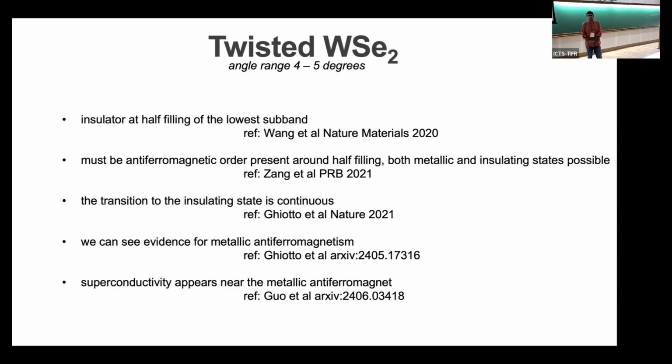One final question from Oscar, and then we should move. How sensitive is your insulator at nu equal to -1 to the external magnetic field, particularly if it's perpendicular? Yeah, that's an interesting question. It's fairly sensitive. By about 3 or 4 Tesla, you generally lose this insulating phase. Something interesting happens at very high field. If you go above 20 Tesla, you have a reentrant insulator, which we believe is actually an excitonic insulator. The Zeeman effect in these things is very strong. At about 20 Tesla, you have an enormous Zeeman effect to the point where you almost spin polarize the carriers, but not quite. And then you can get an excitonic insulator.